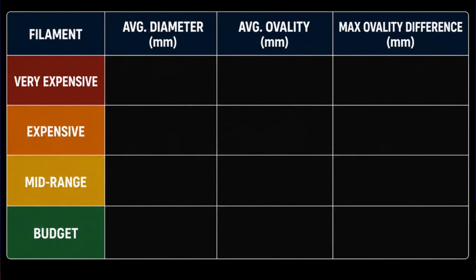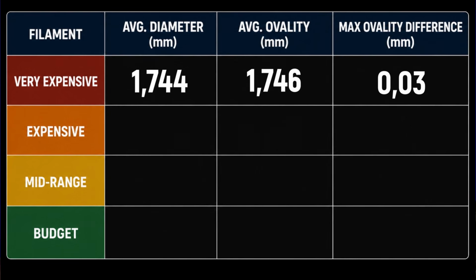In my test, the average diameter of the very expensive filament was 1.744 millimeters. This is very close to the optimal value of 1.75. The ovality was not bad at all either. Its average was 1.746 millimeters, and during the 30 measurements I made for ovality, the maximum diameter difference was only 0.03 millimeters.